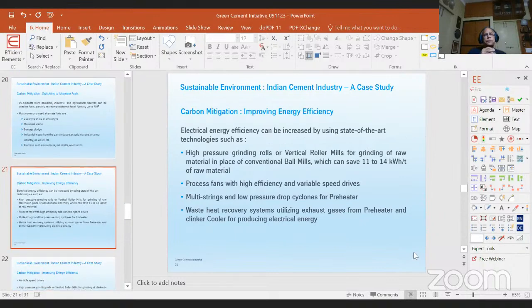Then again, staying with carbon mitigation, there is improving the energy efficiency. Now, obviously, as I mentioned, when you improve the energy efficiency, you reduce your power draw from the grid. So indirectly, you reduce the fossil fuel utilization in the power plants, and then you reduce the carbon footprint. So this is contributing, as I mentioned, 55, 35, and 10. So almost 10%, but still it is a significant percentage of the total CO2 contribution.